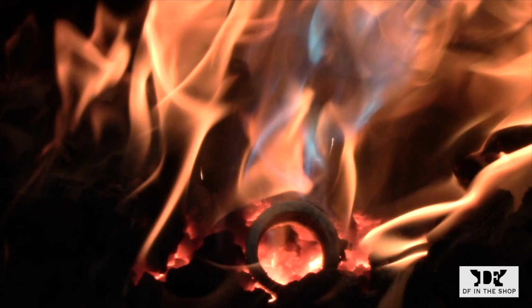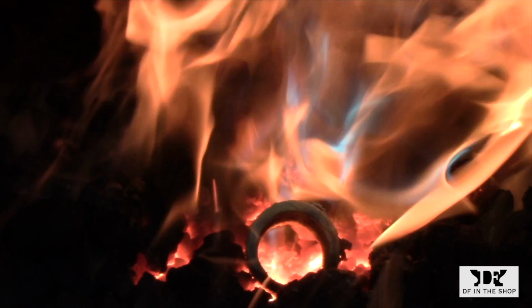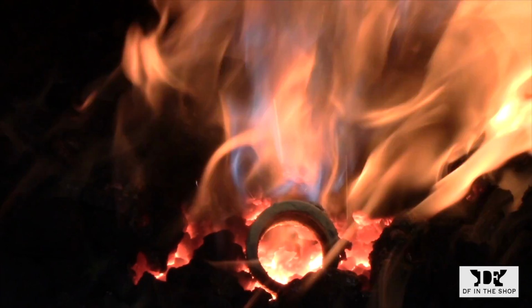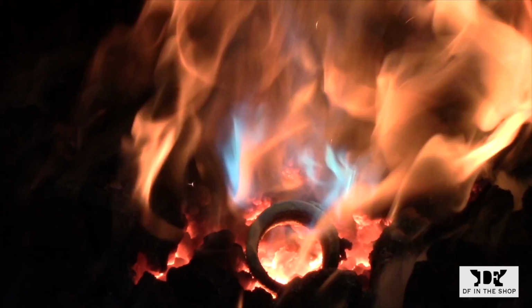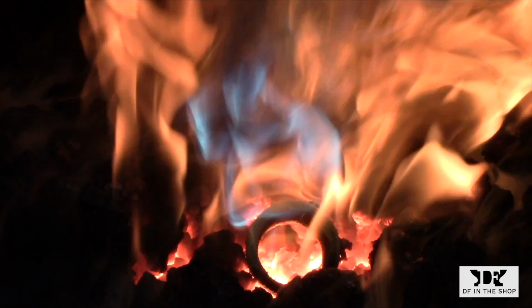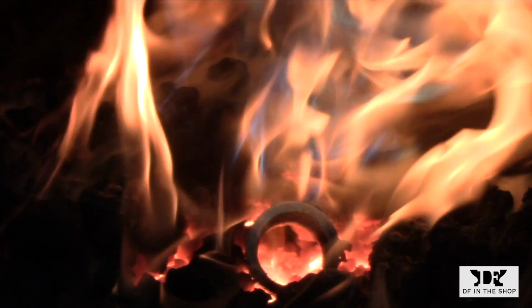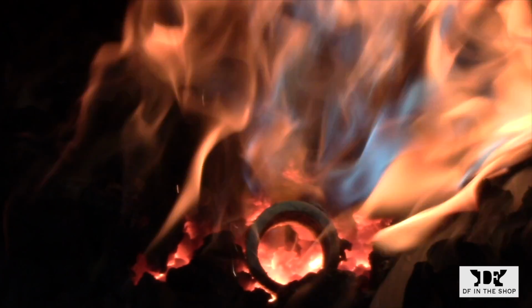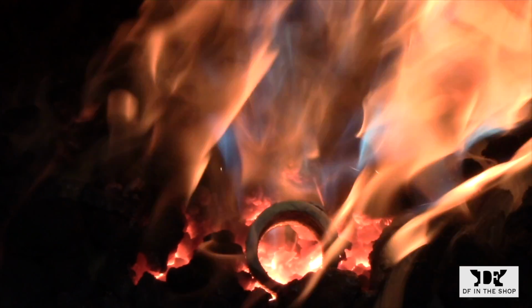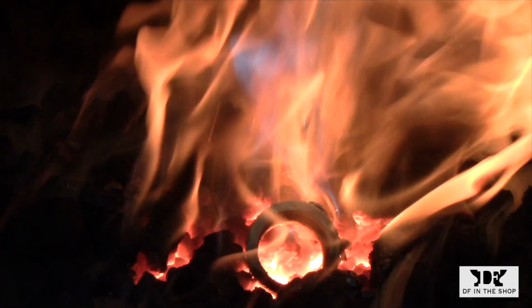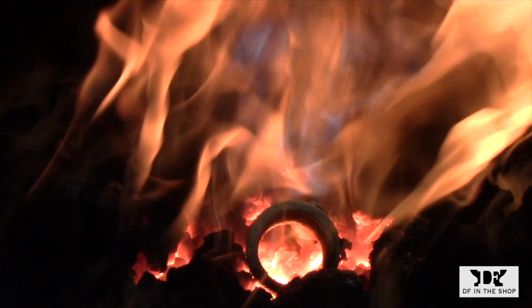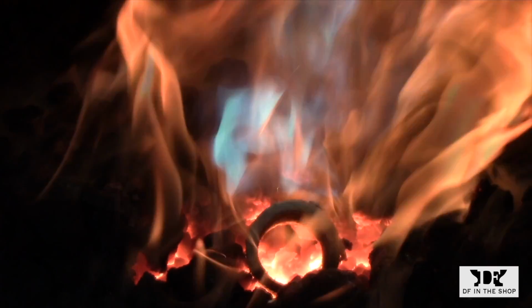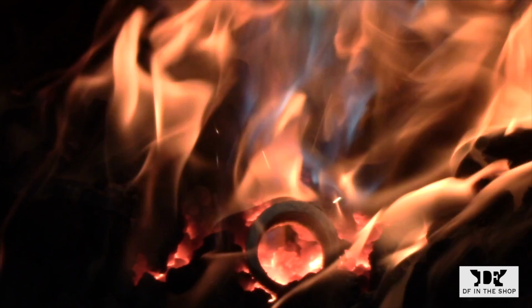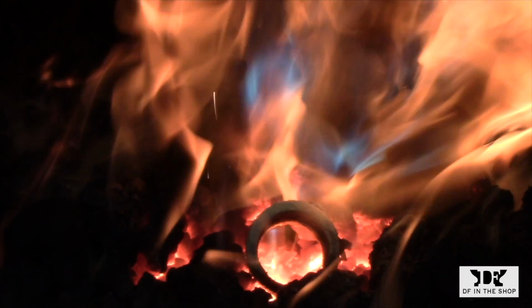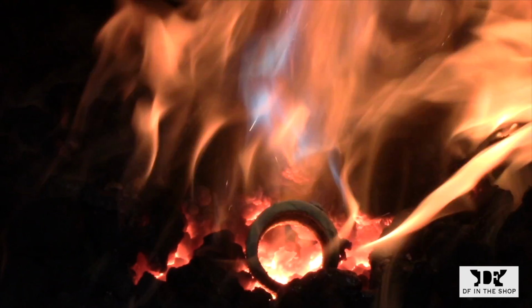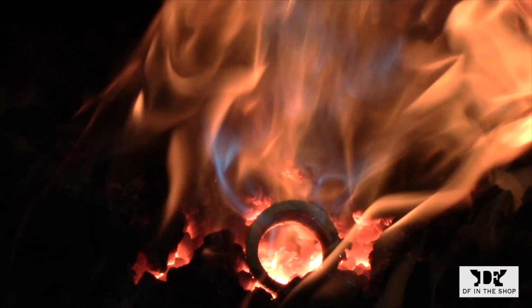But zinc isn't the only metal that you have to worry about. Chromium is also a very toxic metal, and you're exposed to that every time you're welding stainless steel. Prolonged exposure to cadmium can result in liver disease or emphysema, and cadmium is very, very common in paints. Beryllium is another metal known to cause metal fume fever, and that's very common in some copper alloys and aluminum alloys. This piece of galvanized pipe was also painted several times, so chances are I have fumes developing here from all of the metals that I've listed here.